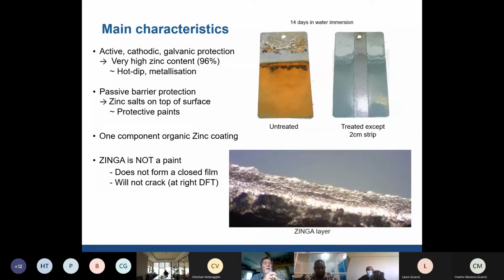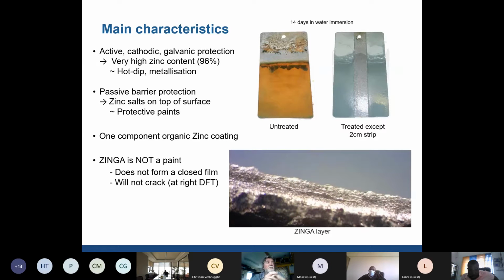Secondly, you have a passive barrier. So you have the active zinc that wants to dissolve to protect the steel. But because it forms a barrier, this barrier is actually a layer of zinc salts, zinc oxides, and within a few weeks it forms zinc carbonates, and the zinc carbonates make the zinc coating very tough. We challenge people to hit it with a hammer and try and crack it or knock it off, and they can't do it. As hard as they can hit that zinc, it will not crack. That's how tough it is.